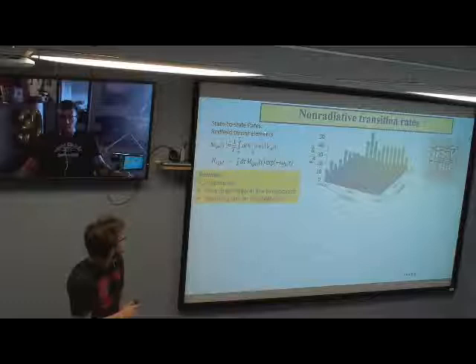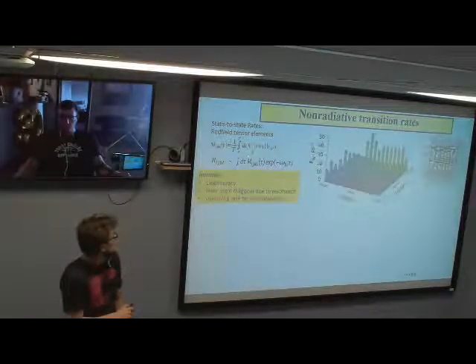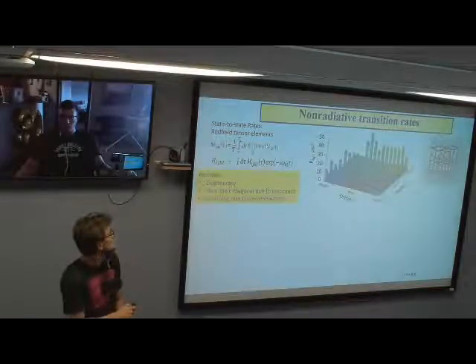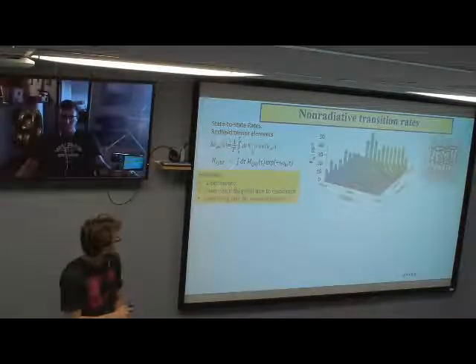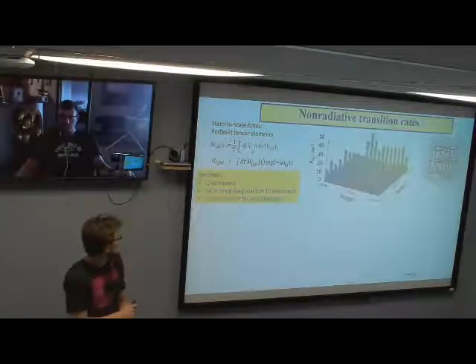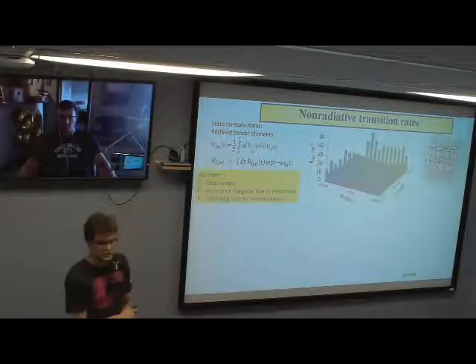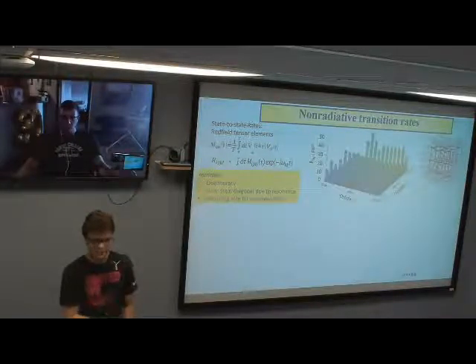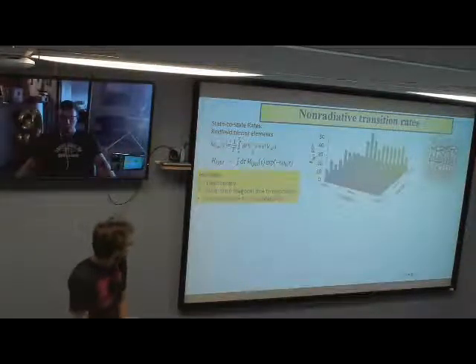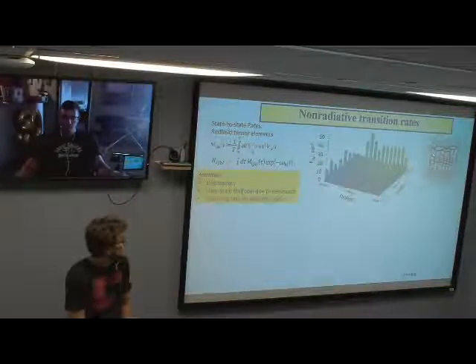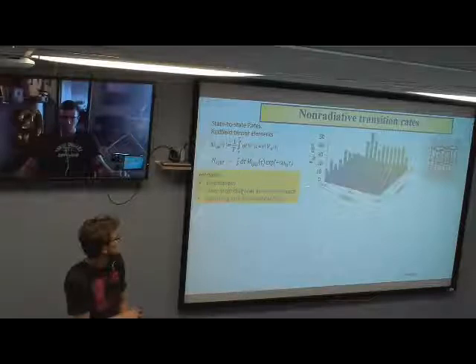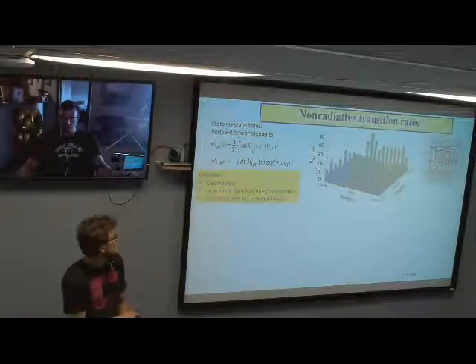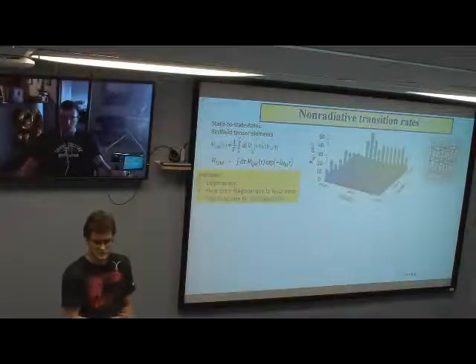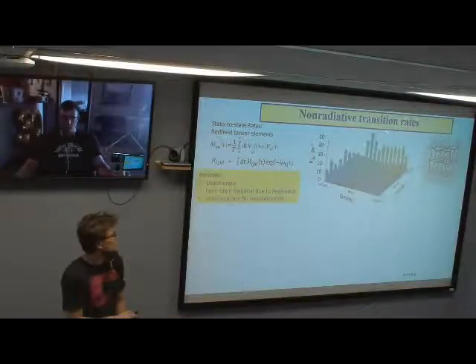And so this is the technical jargon of how we compute non-radiative transition rates for carrier cooling. These Vs are our non-adiabatic couplings, which we compute on the fly. So we take the coupling at one time and later in time, then take an autocorrelation of it. If you take the Fourier transform, you can get transition rates between states due to phonon electron coupling, which is diagrammed here in this tensor. This axis and this axis represent orbital states, and then the z-axis, or the tall axis, represents rates of transitions. So the higher the peak, the faster the rate goes.